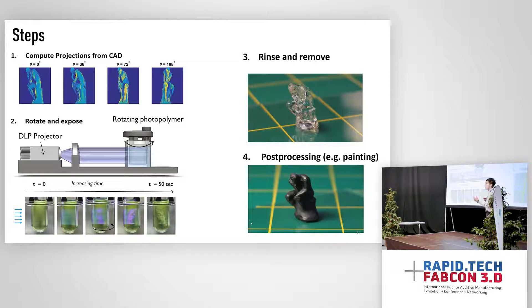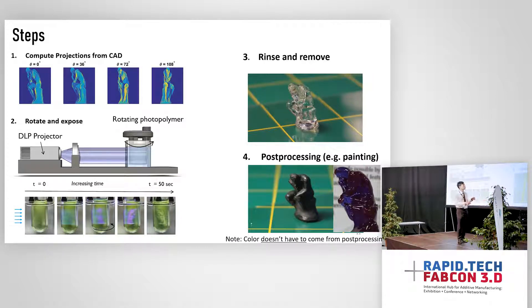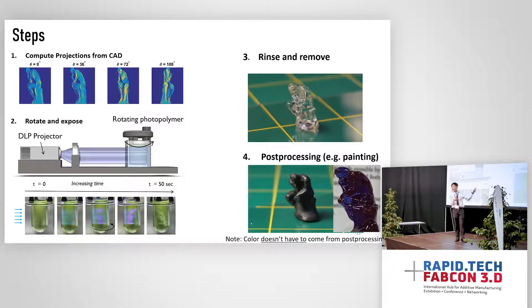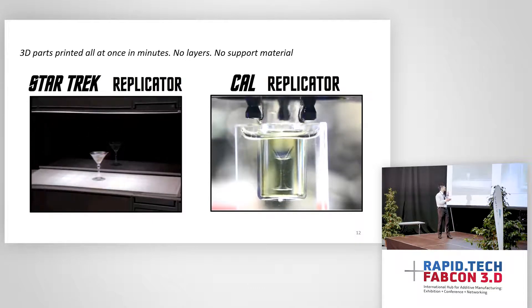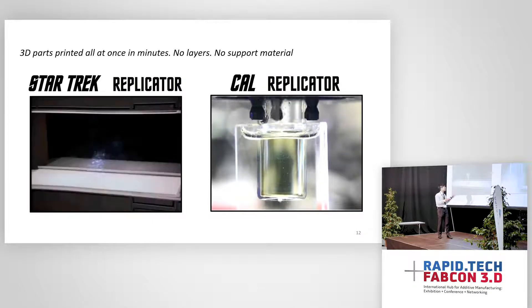Can we get opaque objects straight out of the print? Yes, actually we can. You add a dye to the volume to color it, where the dye doesn't absorb the wavelength of light used for patterning. For example, if you are patterning with UV and the dye doesn't absorb UV, it can be completely opaque in the visible range and you can still get your object. It really looks like a Star Trek replicator — you can see colleagues printing a glass container, just like in the movie.